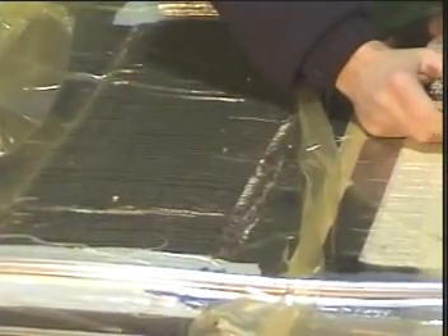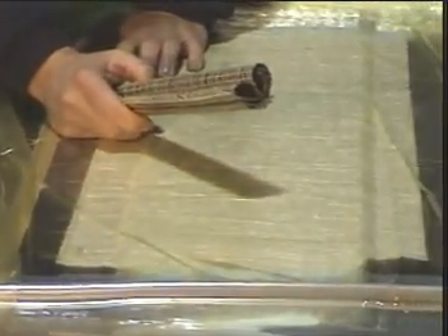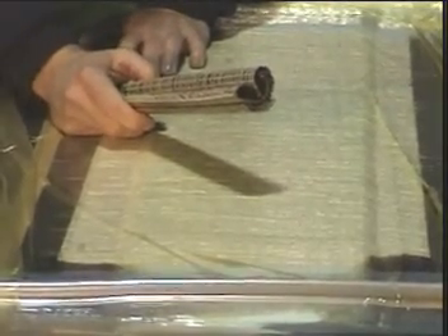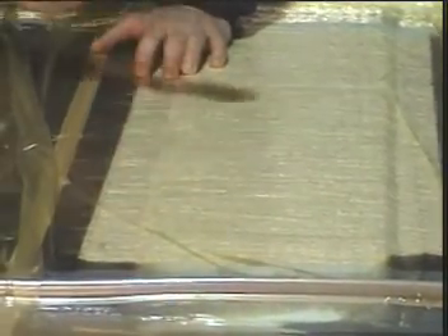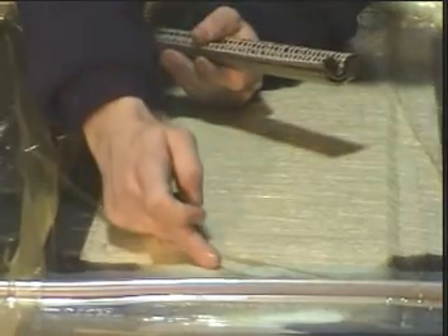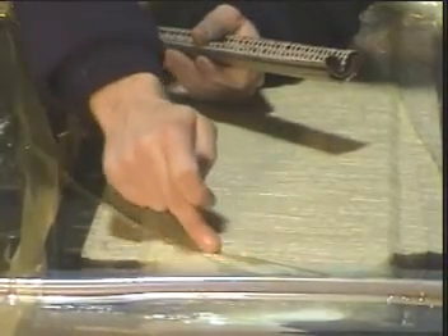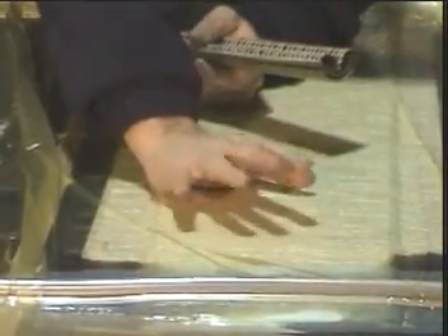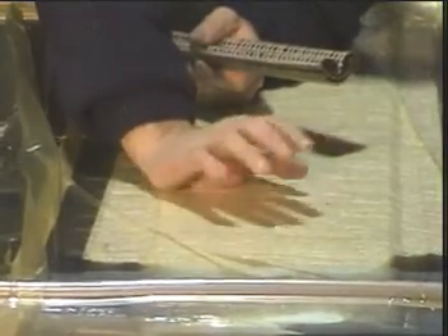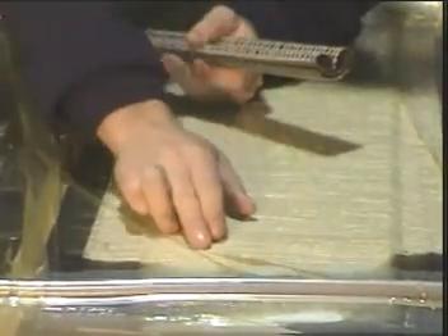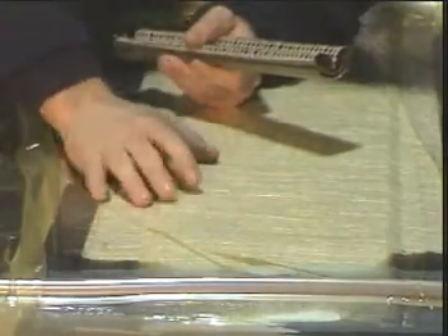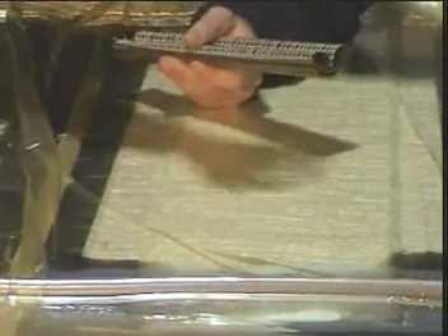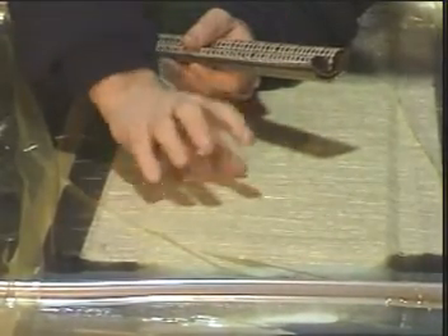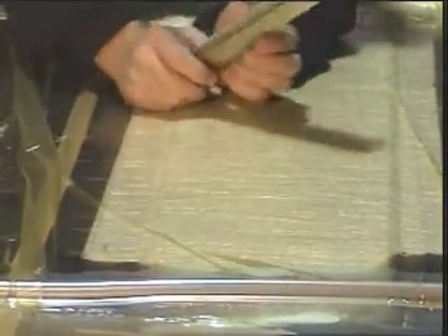In our glass panel, we've moved about, gosh, a couple of inches. Maybe an inch at the most. And you can see actually the resin infusion starting to go a little bit bad here, starting to run up into the wrinkles. This is what happens when resin infusion goes too slow. Things go wrong. Resin begins to run in wrinkles, it creates islands, they create dry spots. The slower infusion goes, the lower the permeability, the bigger the problem.